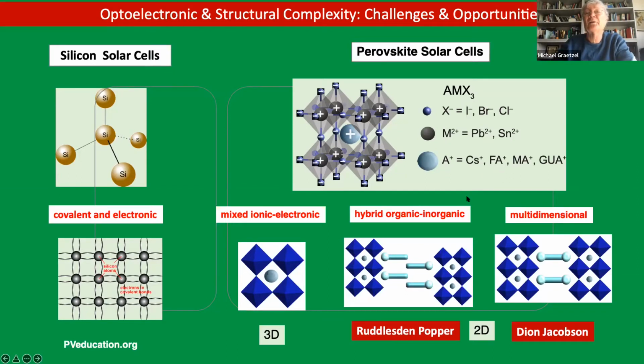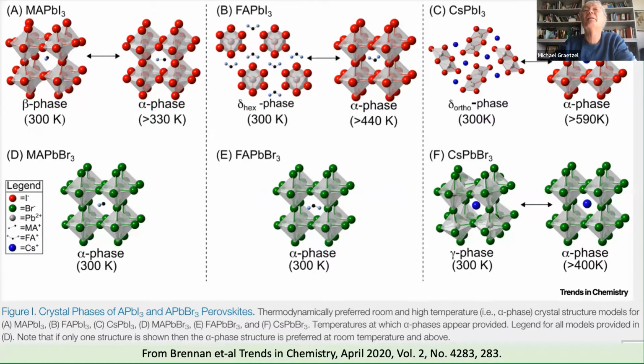And there are also these 2D structures. If you use a large cation like an alkyl ammonium surfactant, then you make a 2D structure, and they have played a role as a protective overlayer in the recent development of perovskite solar cells. A lot of people now focus on formamidinium lead iodide, which is actually the preferred material.